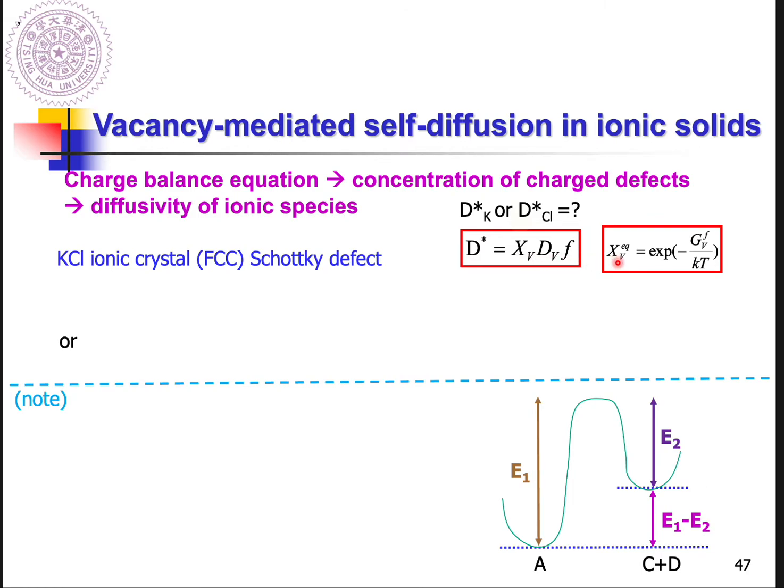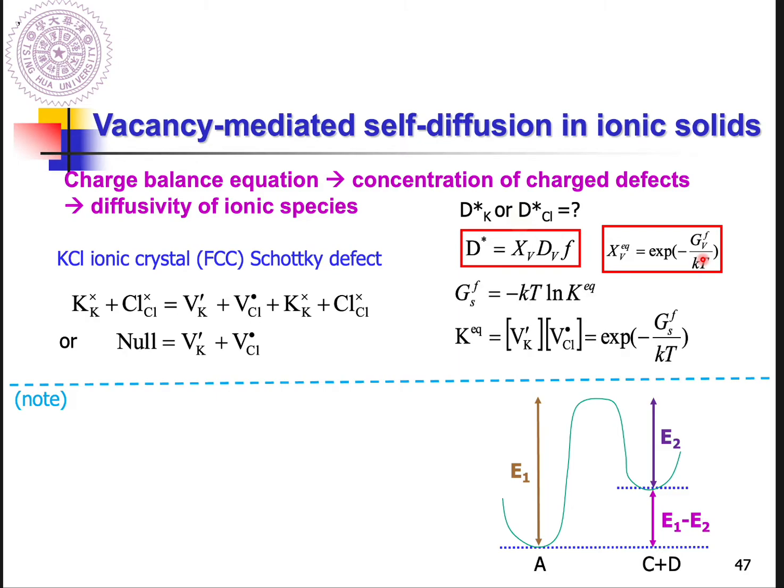Under thermal equilibrium, the vacancy atomic fraction equals the exponential of minus the vacancy formation energy over kT, right?